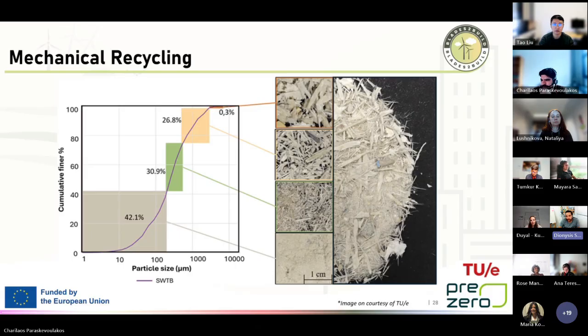As Anna already said, we used some large industrial scale shredders to break down the quite large wind turbine blades into smaller fragments. This was performed by PreZero initially, and then they were distributed to our project partners. Subsequently, TU/e made this characterization, this different classification based on the different fractions per particle size, which was very useful for us because the smaller particles that you can see on the bottom of your screen were used subsequently in the new products that we developed, while the larger particles were used for the chemical and the thermal recycling due to size limitations.